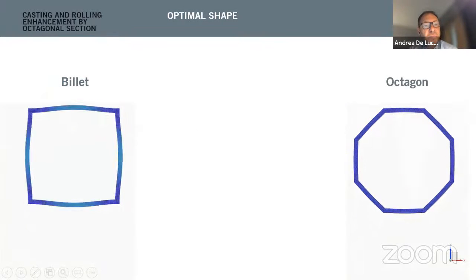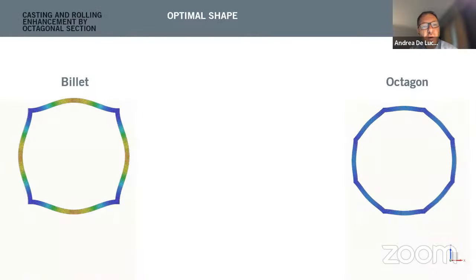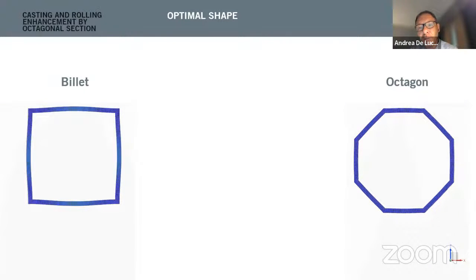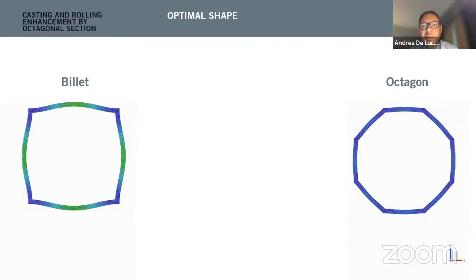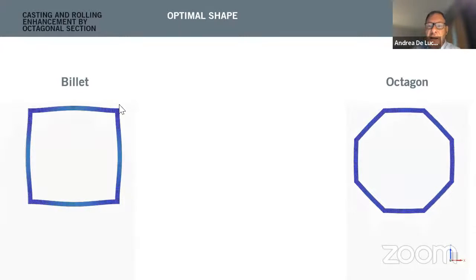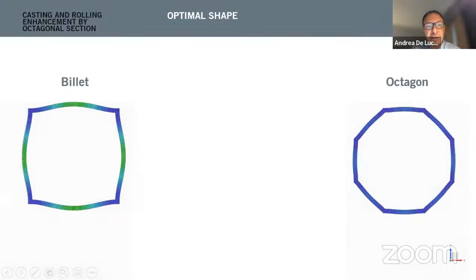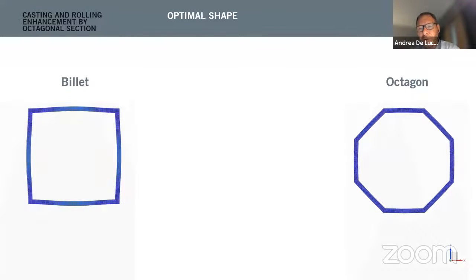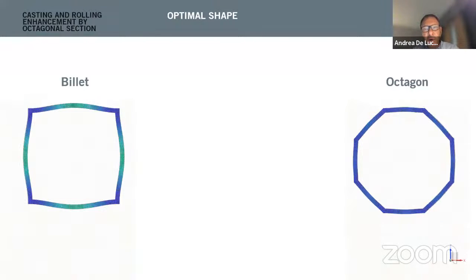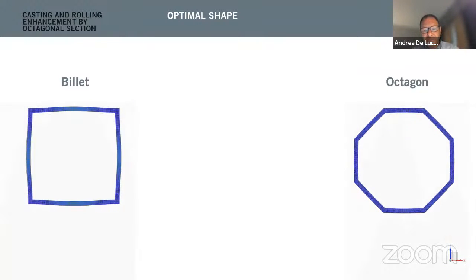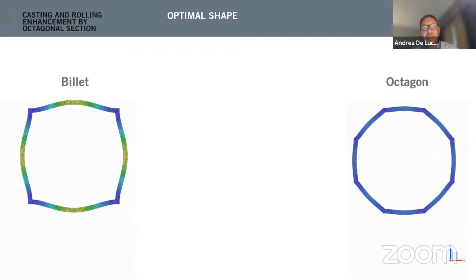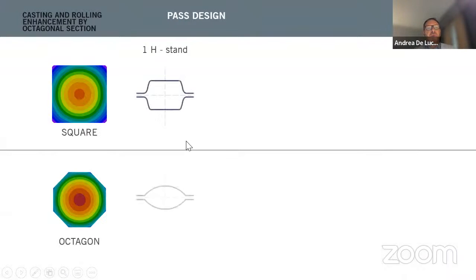You can see here the bulging deformation of the square billet and the bulging deformation of an octagon billet, which is extremely reduced. And what does this mean? It means that I don't need containment rolls at the exit of the mold anymore. So one can say, why not a circle? Why octagon? Well, a circle is perfect. You don't need containment, agreed, but it's very difficult to cast, has no restraint in the mold, and very easily stops touching the mold and starts to have longitudinal cracks and all these problems that caster people know.